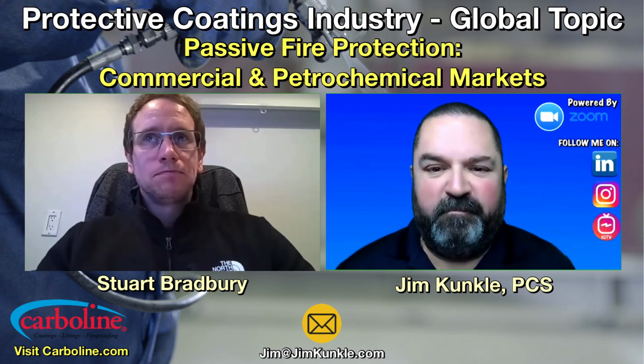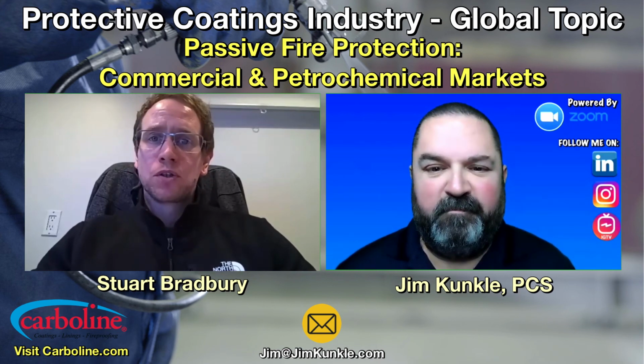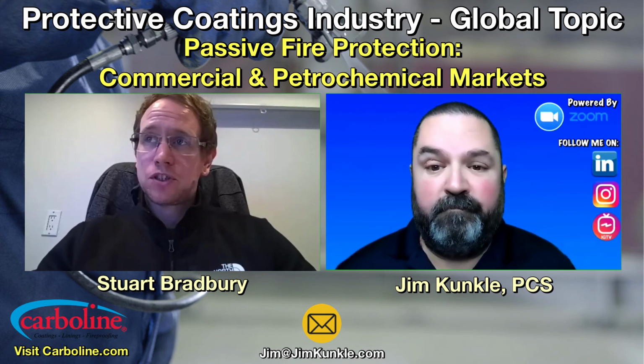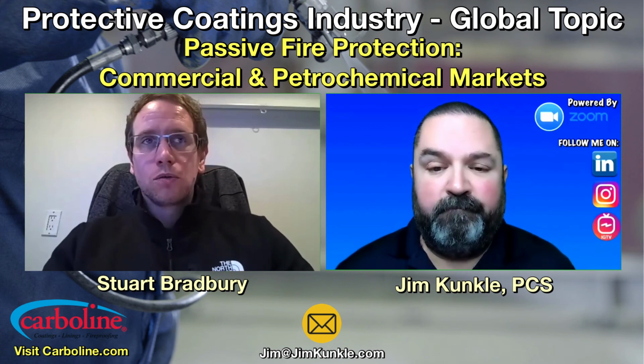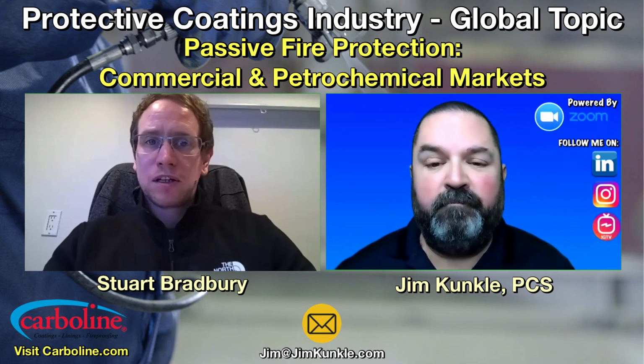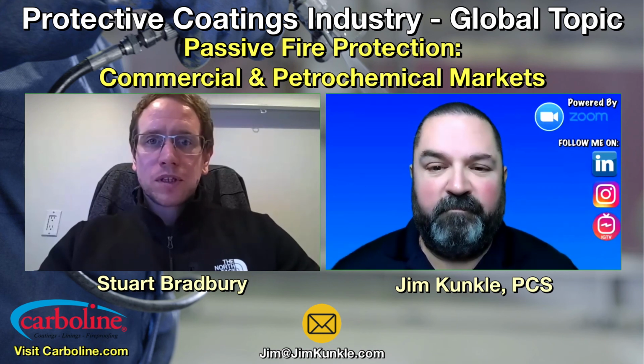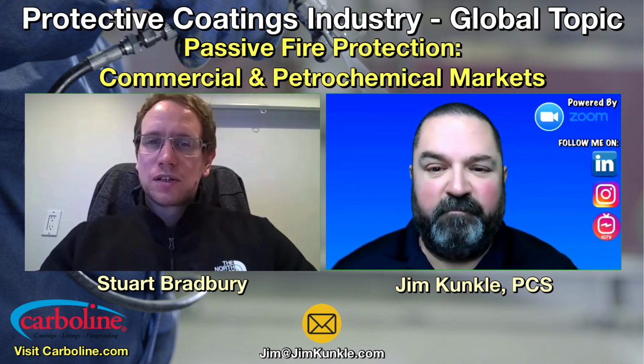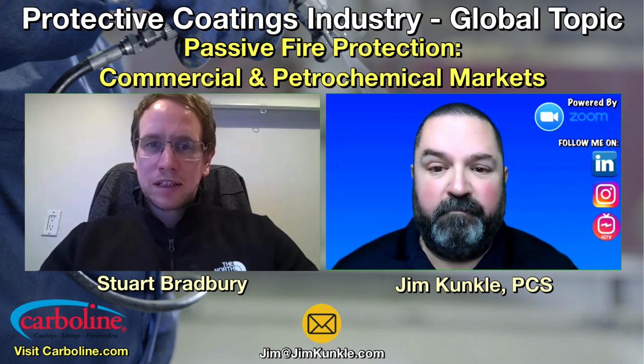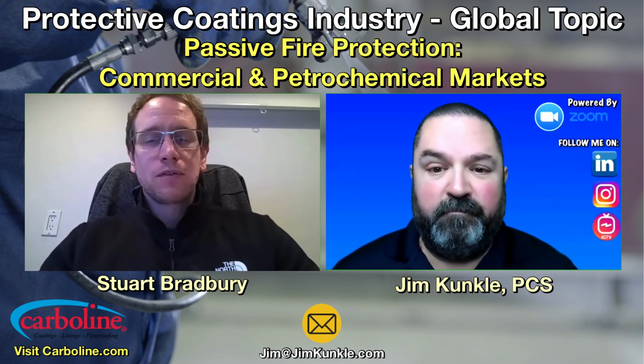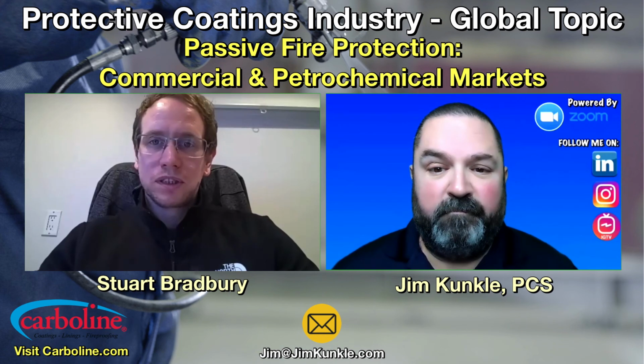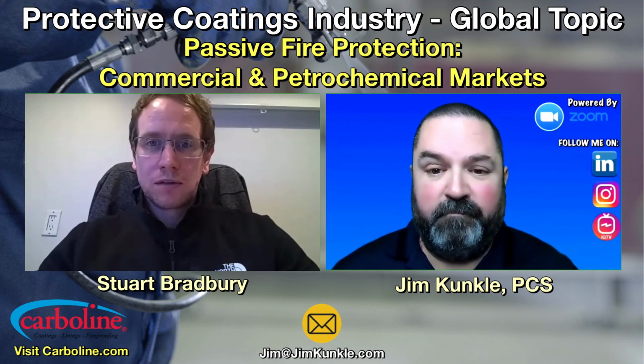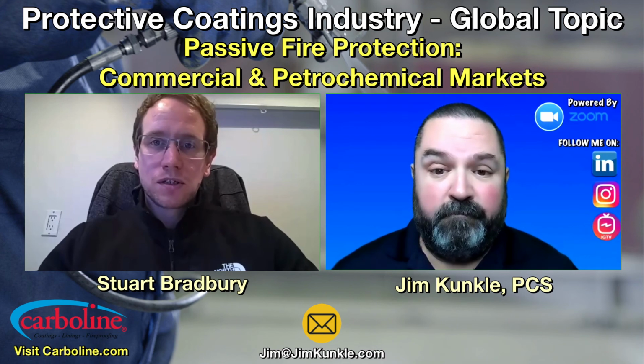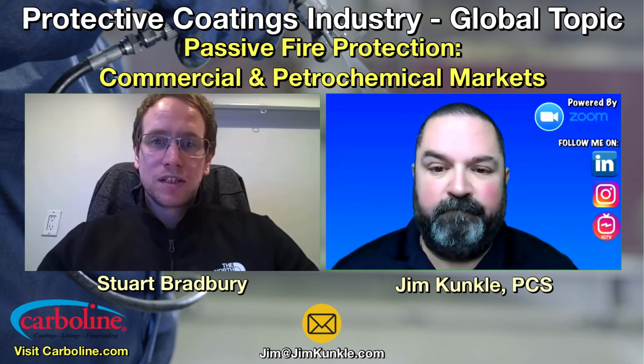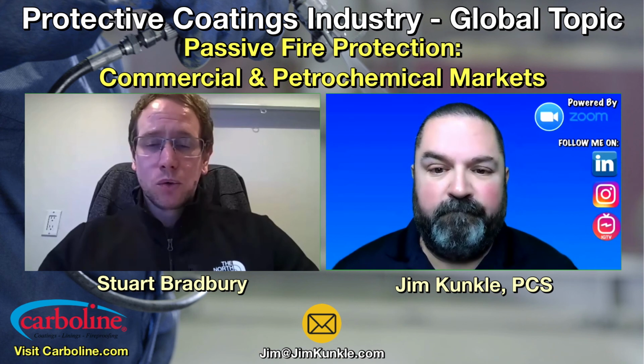So I suppose it's important for everyone to understand that materials will weaken with an increase in temperature, and steel is no exception to that. So carbon steel loss of strength, dependent on the grade, is generally accepted to begin around 300 degrees Celsius and increases rapidly thereafter. So by 590 degrees Celsius, steel will retain only 50% of its yield strength and 45% of its stiffness, which negatively affects its ability to support or carry a load.